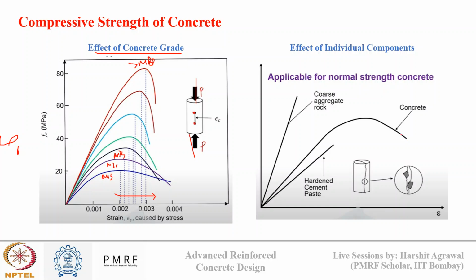In the second figure, we can see the same stress versus strain profile, but for different ingredients of concrete and concrete itself. We see aggregates are stronger in compression, and they have a very steep slope. So you can see they have a higher strength and they achieve the strength at a lower strain value, while cement paste is weak in compression, but has a larger strain, and concrete comes in between these two types, lying somewhere in the middle.